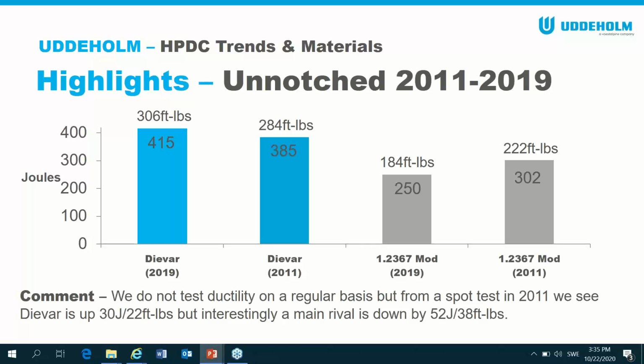Often I hear that a 2367 is superior to die bar for toughness. Blatantly not true. And just to show you that, if we take a 2367, a high quality one from NADCA, we can see here that this is a ductility test, so this is unnotched. And we can see here that we're getting 306 foot-pounds in 2019 when we tested it, and in 2011 it was 284 foot-pounds. But what you're not being told here is the machine's capacity is 450 joules.